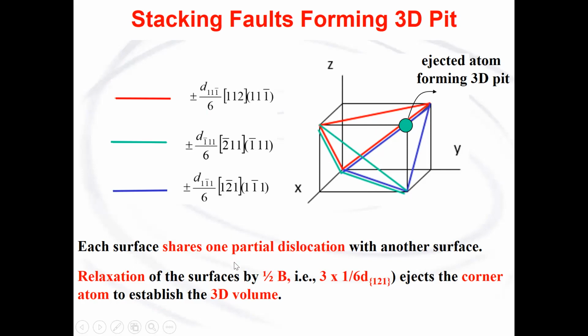And what's interesting is that each one of these surfaces shares 1 partial dislocation. And this reduces the energy and allows for relaxation of these surfaces. And so this relaxation can actually eject the atom that's at the corner here. And when this ejects onto the surface, then we can actually form the three-dimensional pit by forming a three-dimensional volume.